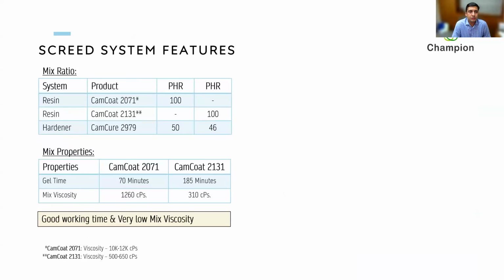I'll talk about the system's features. So we've tested it both with a basic liquid resin, which is 2071, as well as a low viscosity resin, which is 2131. The mix ratio is pretty consistent. It's about 50 parts, whether you use either of the systems. When you use the low viscosity system, the mix ratio can fall a little bit, but it's not very dependent on the mix ratio. It can still be used at 50 parts. What you will notice here is that the gel time can vary quite considerably, and you can have a very different level of mixed viscosity, which can impact your filler loading. You can add a lot of filler into the system based on the type of mixed viscosity you get.